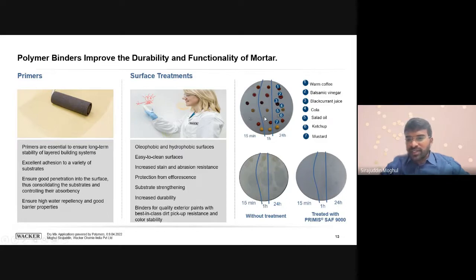See, here's a test that we conduct in our lab, where we have used multiple eatables, we can say, like the ketchup and mustard that we regularly use in our kitchen, which generally fall on the wall. And we have tried it. If it is not treated with any polymer, the stains will remain on it. See, this is cleaned after 15 minutes, after 1 hour, after 24 hours. So the stains will remain as such.